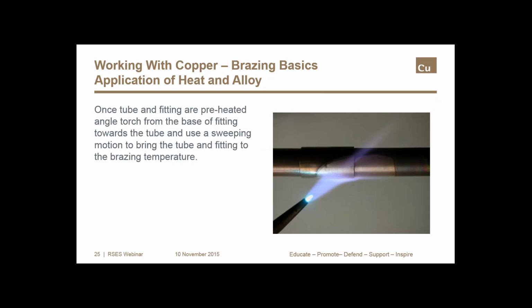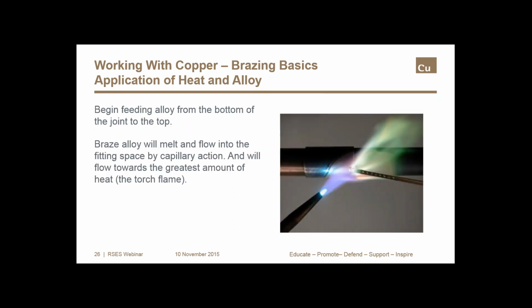When the tube and fitting assembly has reached the braze temperature, the flame should be angled toward the tube. And now this assembly is ready for braze alloy. So we now have the joint heated and the flame at the base of the fitting angled toward the tube. The filler metal is added at the bottom where the tube enters the socket of the fitting. Heat and capillary action will draw molten alloy into the joint from bottom to top.